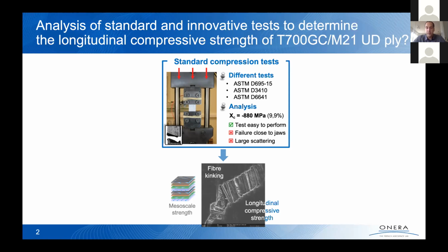The test is pretty easy to perform, but you are going to observe that the failure often occurs close to the jaws. It has been clearly explained previously, because at the end of the jaws, you are going to generate in-plane shear gradient, which are going to interact with the longitudinal compressive stress and induce premature failure at the end of the jaws. Therefore, you are going to obtain a pretty large scattering. In that case, the covariance of the test was around 10%, which is pretty high. Moreover, because the failure occurs close to the jaws, most of the time you are going to obtain pretty low value of the strength. In that case, it is around 900 MPa.